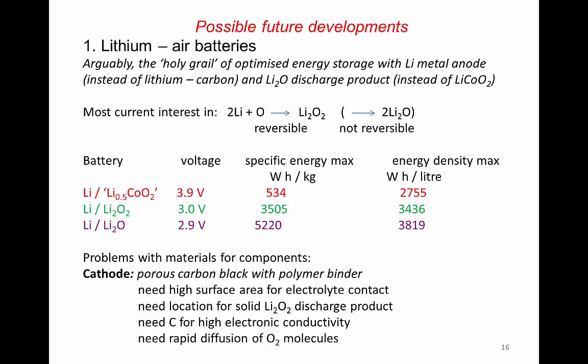But there are many problems with the materials. It's basically a material science problem that needs to be solved in getting suitable components that are stable and give reversible performance. So the cathode is usually a porous carbon black with a polymer binder, similar to current anodes in lithium batteries. We need a high surface area for the electrolyte contact. We need a location for the solid lithium peroxide discharge product. We need carbon for high electronic conductivity, and we need rapid diffusion of oxygen molecules so that they can come from the air to react at the electrolyte surface with the lithium ions from the discharge.